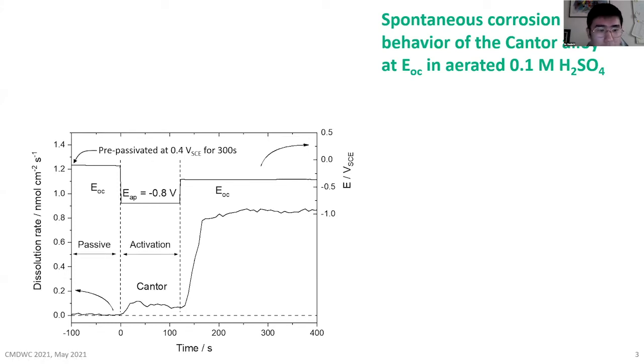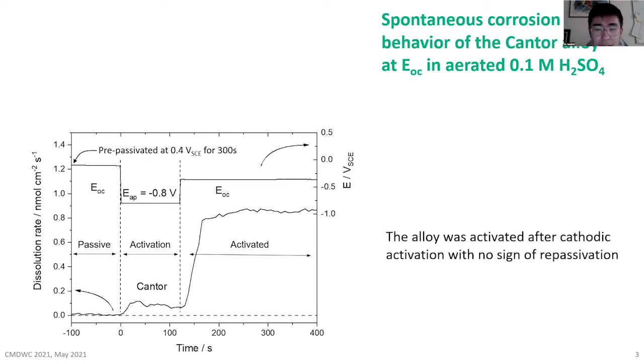And then we apply a cathodic potential of minus 0.8 volt, because we would like to remove the passive film, and we detect some dissolution. After the passive film breakdown, we release the potential to open circuit, and we see the dissolution increase rapidly to a constant value higher than in the passive state. So we can tell that the alloy was activated after the cathodic activation step, with no sign of repassivation.